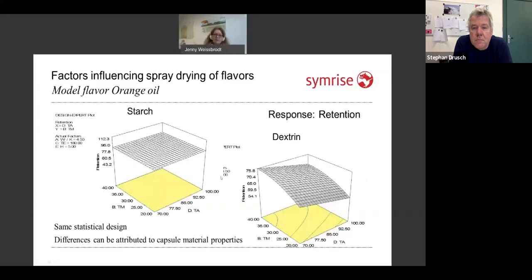The same materials for the encapsulation of orange oil. You will see here in the first picture that whenever you have a good emulsion, all the other factors are not really important for a water-insoluble component. Whether you use a low solid content or a high solid content, whether you dry with a moderate outlet air temperature or a high outlet air temperature, it doesn't make any difference at all. For the dextrin, here you have to dry fast. Yes, it's true. Just put in as many solids as you can.